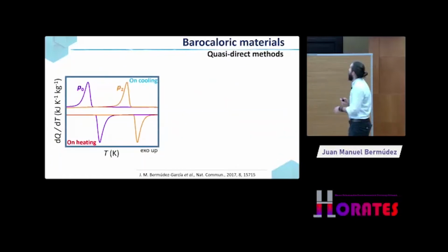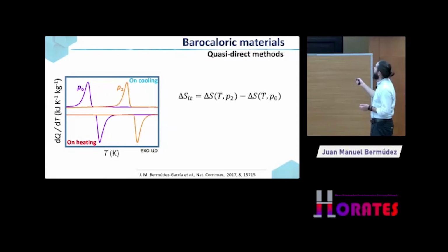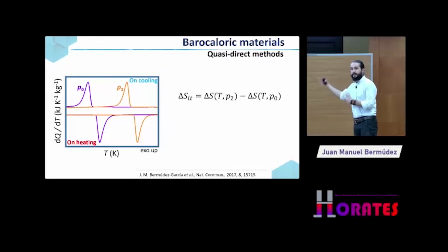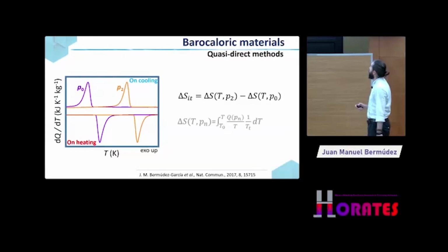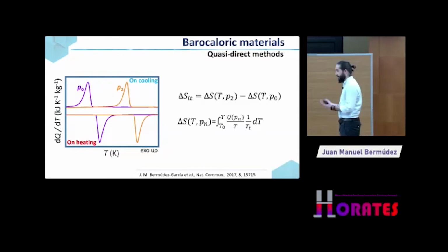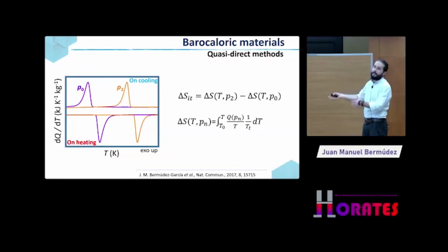For that, what you do is that the barocaloric effect in terms of isothermal entropy change is defined as the entropy change of your phase transition at the maximum pressure minus the entropy change of your phase transition at the pressure at which you start, the ambient pressure, okay? So you have to calculate these two entropy changes, and this is quite straightforward. You just do the integration of both peaks, and then you do the subtraction, right? The integration is gonna give you the enthalpy change of the system, the latent heat, and then you just divide it by the transition temperature, which is the maximum of the peak, and you have the entropy change, okay?